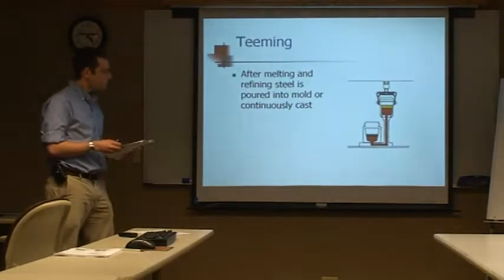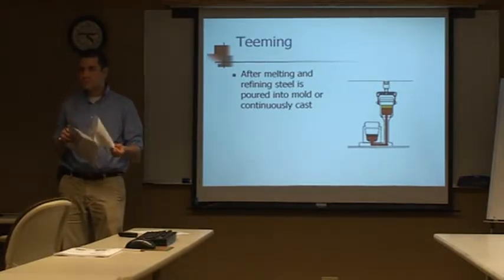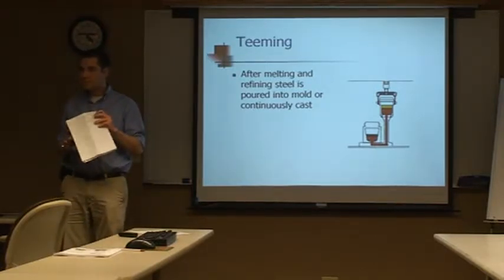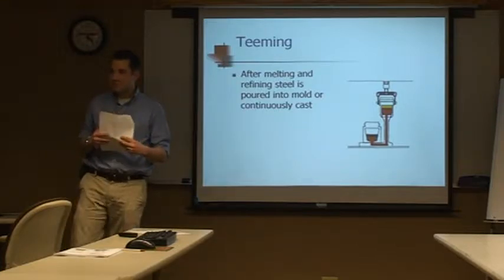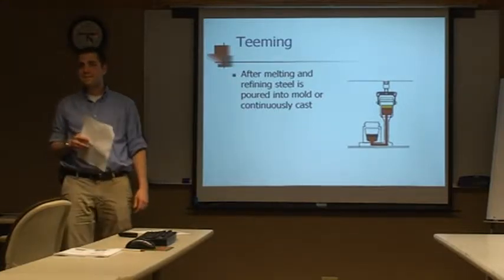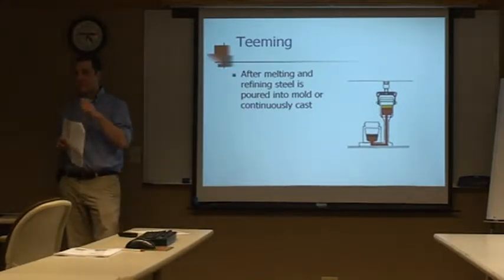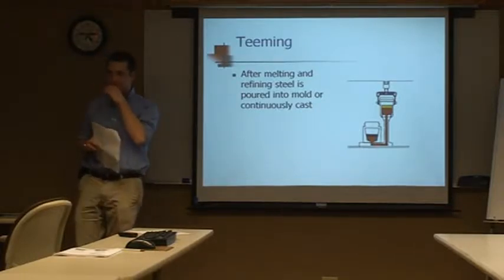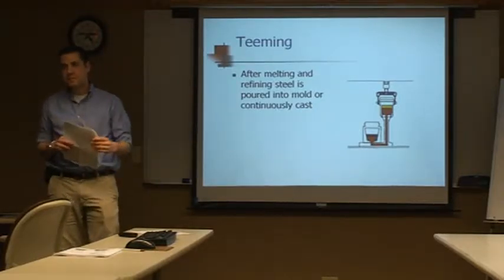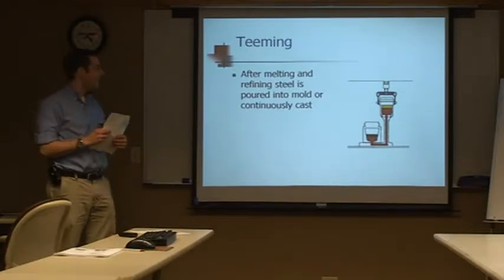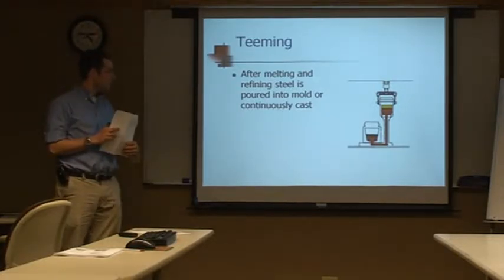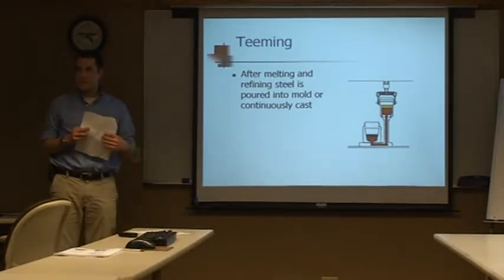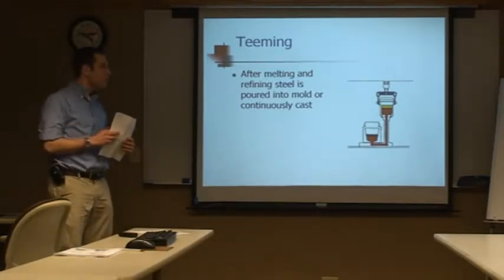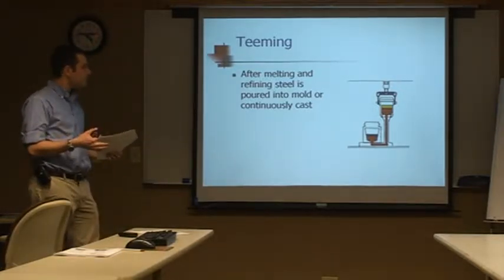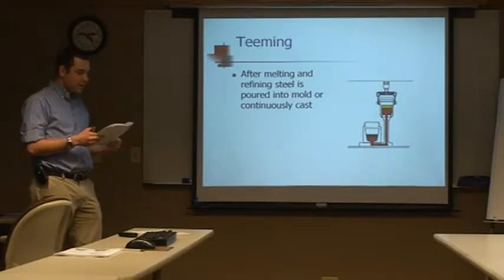The amount of hydrogen we're trying to remove, if it was liquid, it would fit in this cap. Just to give you a scope, it's not very much at all, but just that much hydrogen can wreak havoc in a forging. And we'll talk about that a little bit later. Hydrogen is the enemy when it comes to steel, and very tricky to remove, but through a lot of advanced processes, we're able to get that content very low.